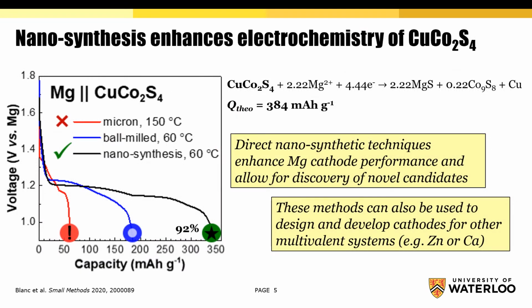The electrochemical performance of these materials clearly shows the importance of curtailing particle size when screening for magnesium cathode candidates. While micron-sized material showed little promise as a magnesium cathode, nanomaterial prepared using the xanthate method achieved 92% of the theoretical capacity of copper cobalt sulfide.